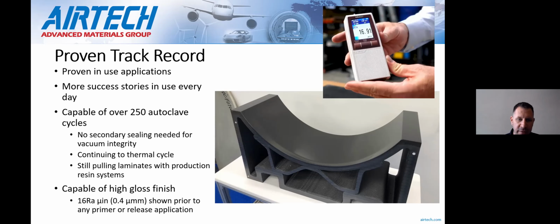But that criteria as we've gone through was, the tool had to meet the same requirements as a production tool might. So it had to be vacuum integral from the first cycle to the last cycle without any sort of repairs or patches or other sealers required. But we've already reached this threshold of 250 autoclave cycles with great success, even pulling laminates along the way and finishing this tool to a high level.